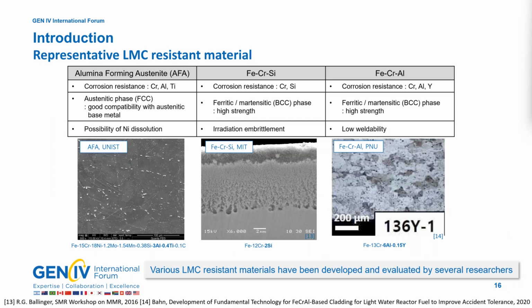The following are several representative LMC resistant materials developed by other researchers. Alumina forming austenite includes chrome, aluminum, and titanium as corrosion-resistant elements and has an FCC structure, providing good compatibility with austenitic base metal. However, there is a concern about selective nickel dissolution due to its nickel content.